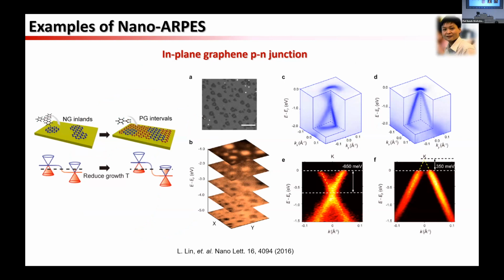Before I get into the topic, we have done a lot of preparation, even way before magic-angle twisted bilayer graphene. We started to study graphene as well. For example, using this method, we were able to discover an in-plane graphene p-n junction. You can see the different contrast that shows the p and n type regimes. Long story short, in the end, this is what we observed. In this regime, the graphene layer is n-type doped, and the Fermi level is about 650 meV above, while the p region is 350 meV below. So the chemical potential difference can be up to 1 eV.